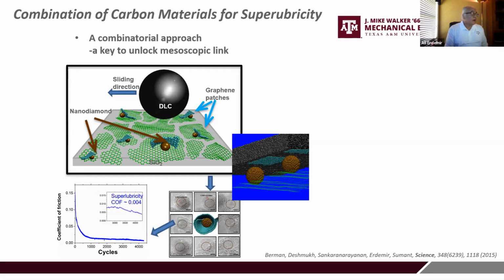When we did very high resolution transmission electron microscopy of these surfaces, we noticed scroll-like formations with diamond nanoparticles right in the center. This gave us the impression that these nanoflakes were attaching to the surface of the nanodiamond, which makes perfect sense since both edges and the surface of the nanodiamond have sigma bonds or covalent bonding possibilities. Once that happens, the rest of the graphene would just scroll to form these rolls.